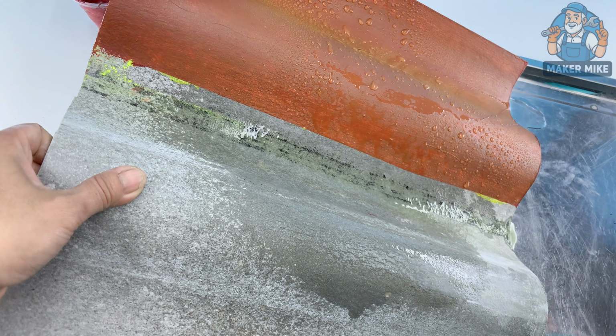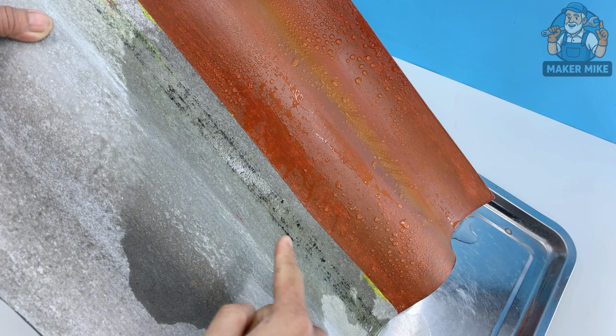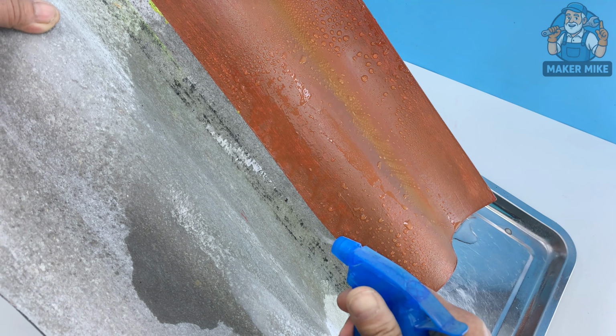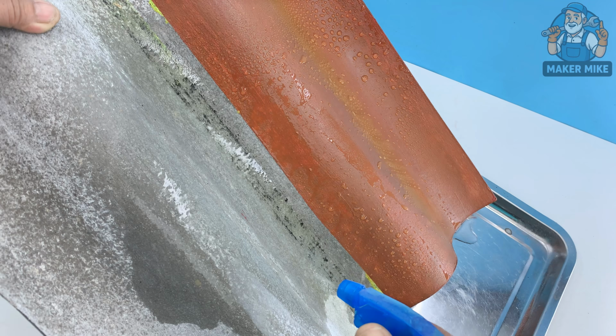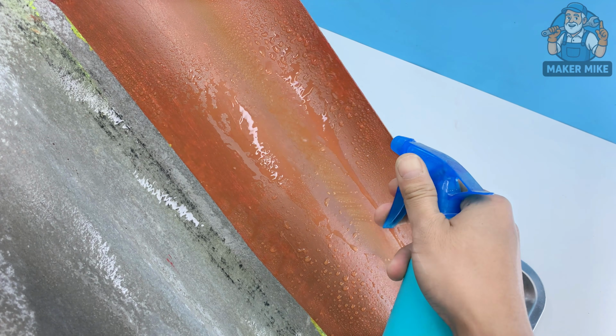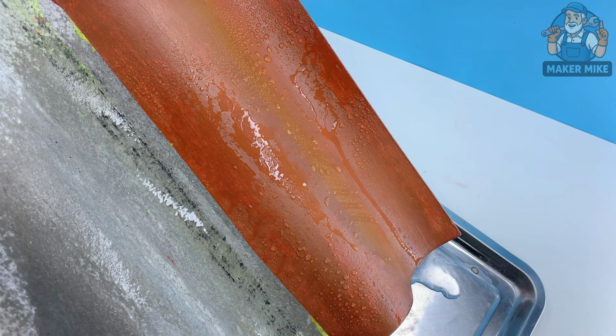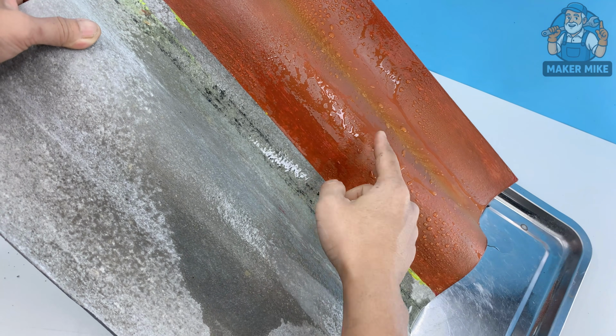Now spray water on the coated side. The difference appears immediately. The water stays on the surface and does not soak into the cement board. The coating prevents the water from penetrating, and the color remains stable without fading.